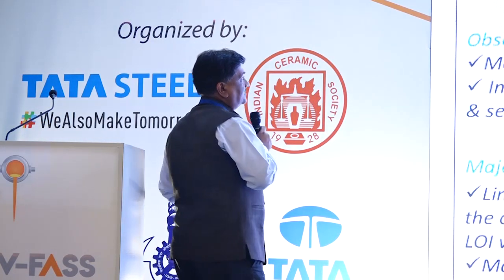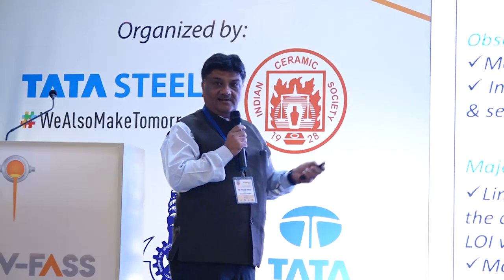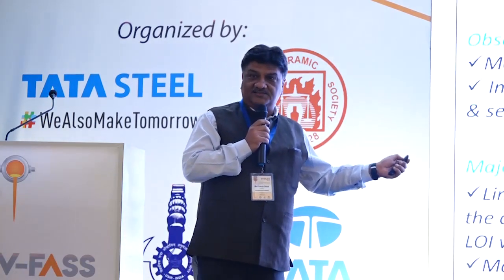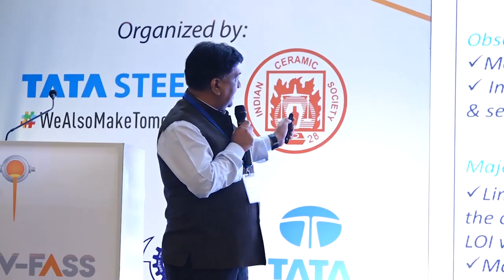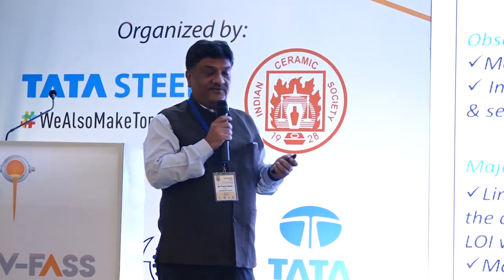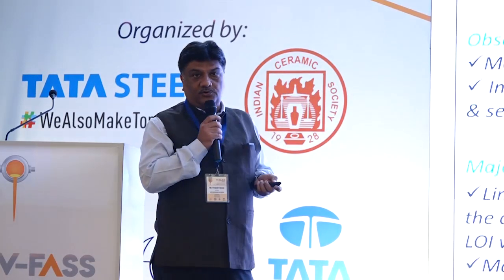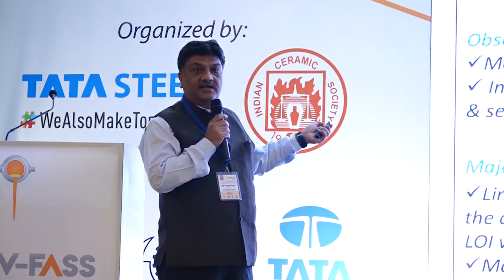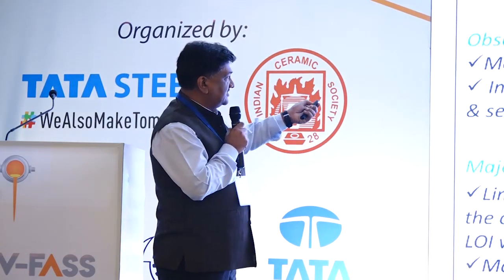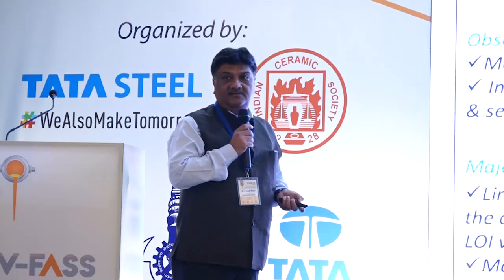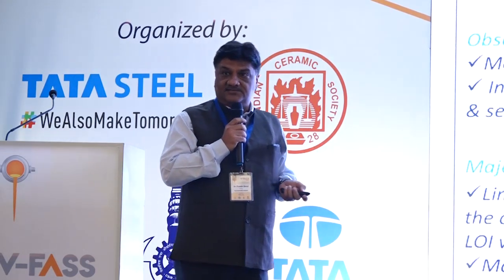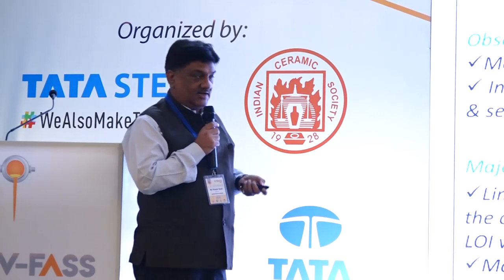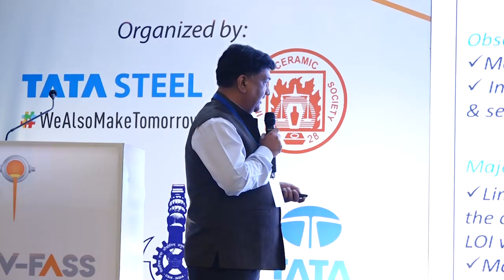Another way is using it as an addition to the kiln inlet. However, this is a patented product from 20 years back. But this can be done, which can benefit us with more clinker output. And of course, the C3S content is higher when we use the LD slag, which can enhance the early strength and setting. These have been evidenced at various laboratory levels, and in our own experiments we were getting those